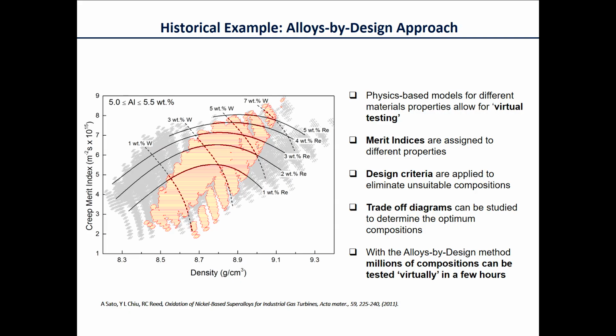We decided we wanted to try to do better than this, and that process involved making many, many calculations on the computer and identifying these kind of ISO fronts here, which will allow us to optimize the composition of the alloy based on merit indices and design criteria to eliminate unsuitable compositions. This was a really nice thing which we did, I think, in retrospect, and we termed this method an alloys by design approach, because we wanted to be able to design alloys for their properties in just the same way, for example, that polymer chemists are able to design new kinds of polymer materials on the computer quite routinely.